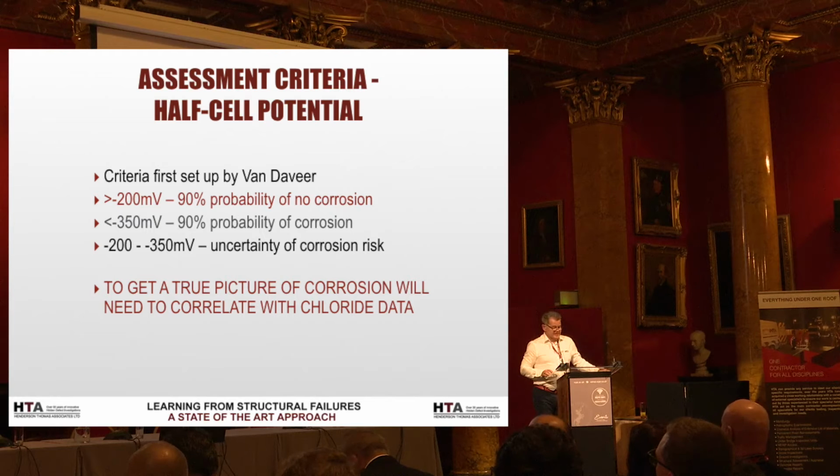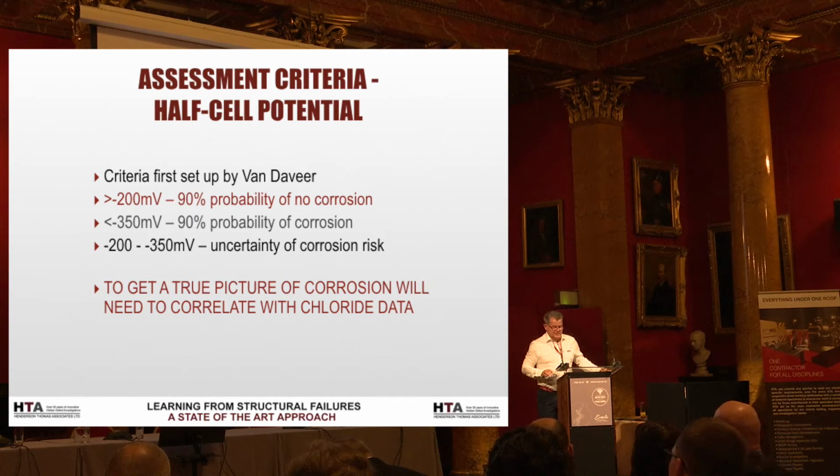However, there are instances where half cells do have certain restrictions, one of them being an increased moisture content in concrete. To give you a brief example, a number of years ago, we tested a lifeboat station which had substantial amounts of corrosion just underneath the boathouse in the intertidal zone. We were asked, however, to test right the way down the bottom of the ramp to see what the condition of the concrete was there. This area would only be exposed 2 to 4 times a year at a very high spring tide and a very low spring tide. Therefore, the concrete was permanently in water, never dried out. And one of the restrictions of the technique is that if you get an increased moisture content in the concrete, it can artificially shift the potential.